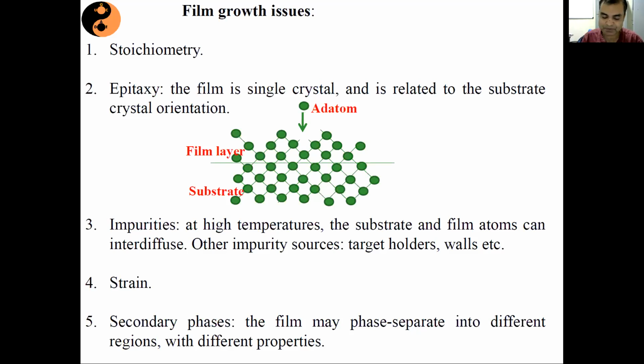Another thing is that how do we optimize the temperature? Remember, suppose if you have to grow a material, any material's phase is stable only in a particular pressure and temperature window. So if your temperature is way away from that window, suppose if I'm making something like BiFeO3, then the grown film can have bismuth oxide phase also, Fe2O3 phase also, FeO phase also, Fe3O4 phase also. And all these different phases are stable in different temperature and pressure window. So to get really a good BiFeO3 film, we will have to optimize the condition in terms of temperature and pressure to get the single phase film of all these materials.